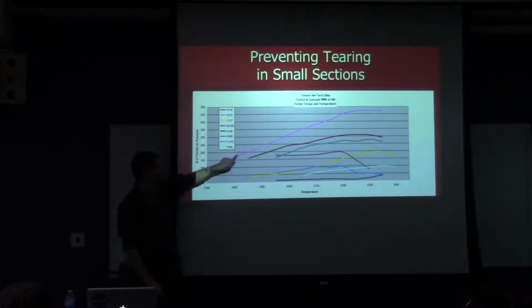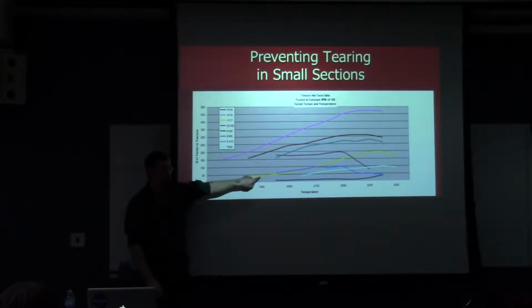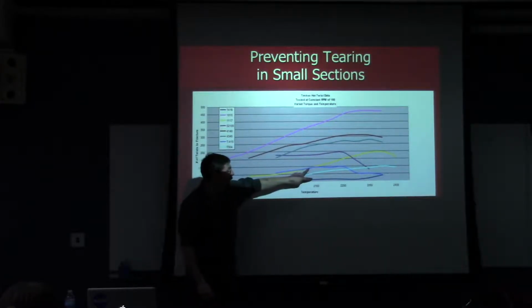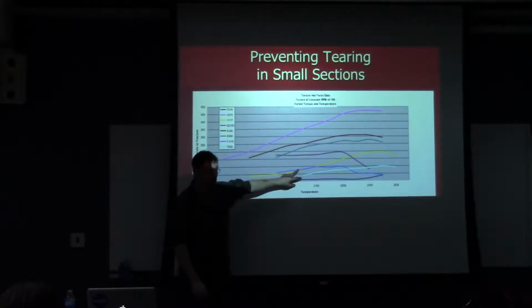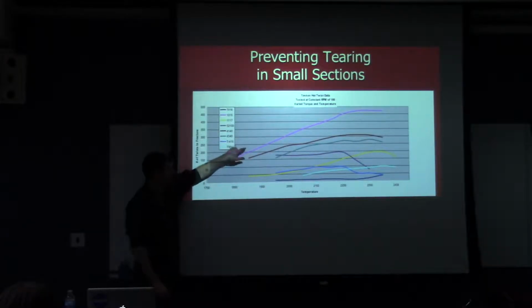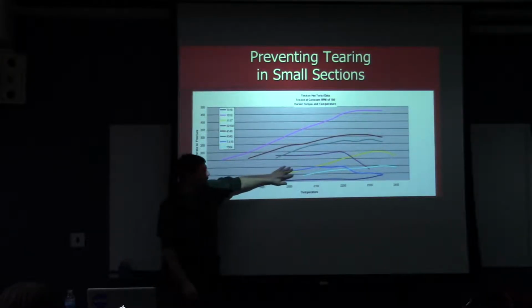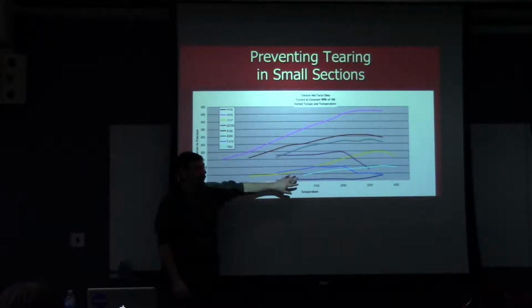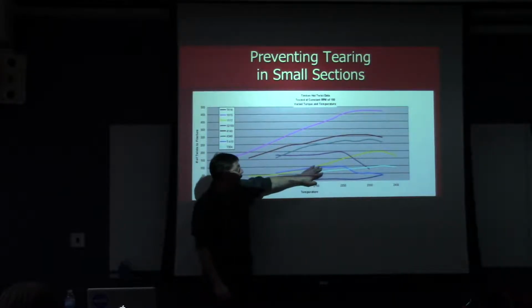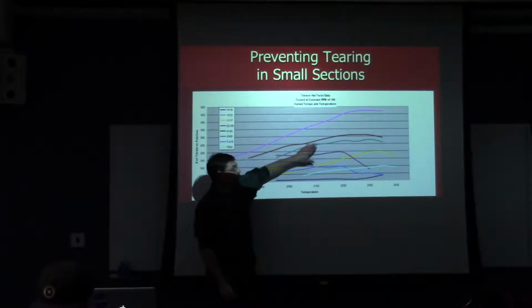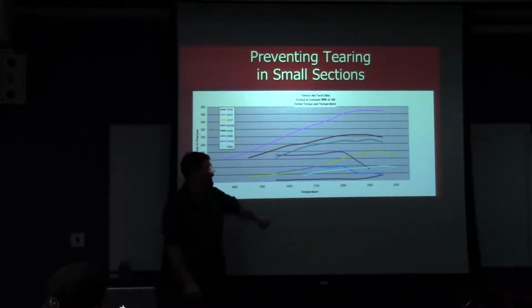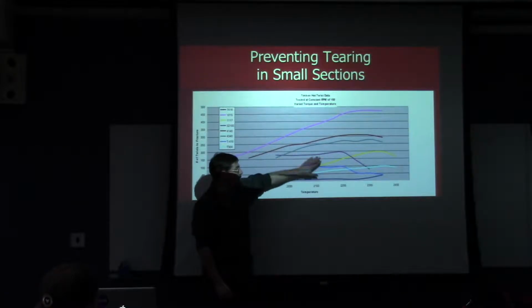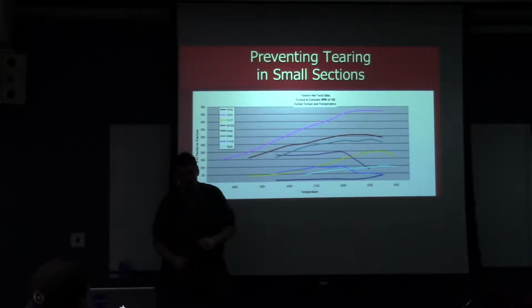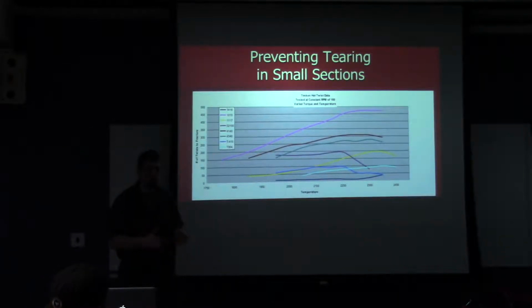Things that I can do with this material, I better not do with this one, or I'll end up with a part that's scrap. Same with these two here. These were the two martensitic stainless grades. We had the T416 and T410. Both of these are very low on this graph. We can see that they're very low, again, in comparison to, say, these materials here, which are low alloy steels. You can do a lot more here than you can here before you cause a problem. So again, you have to be aware of the materials that you're working with and tailor your procedures accordingly.